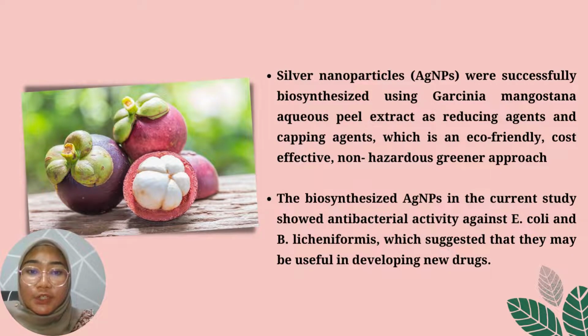In the conclusion, the silver nanoparticles were successfully biosynthesized using Garcinia mangostana, which could act as a reducing agent and capping agent, an eco-friendly, cost-effective, and non-hazardous greener approach. Then the biosynthesis of silver nanoparticles in the current study shows antibacterial activity against E. coli and B. licheniformis, which suggests that they may be useful in developing new drugs.